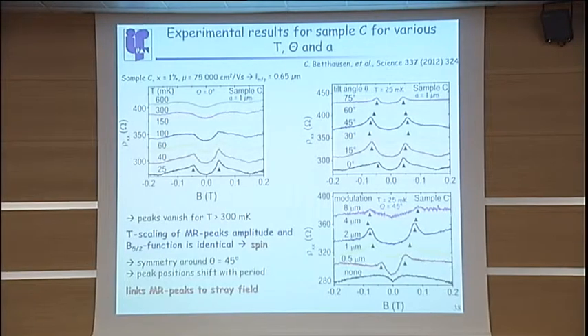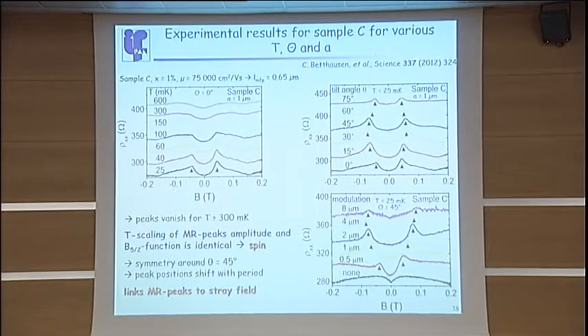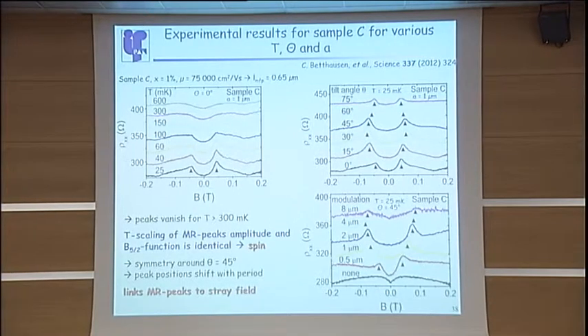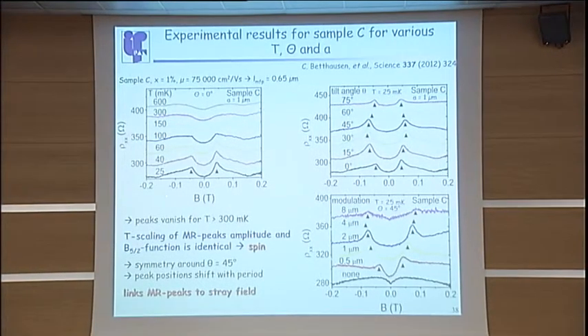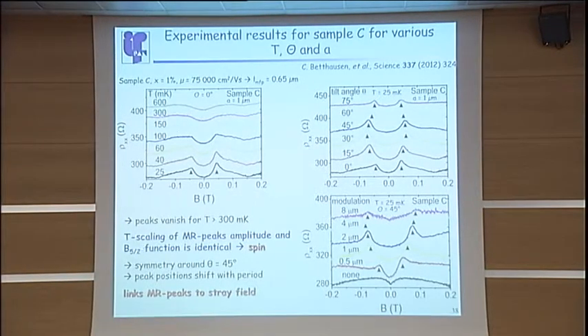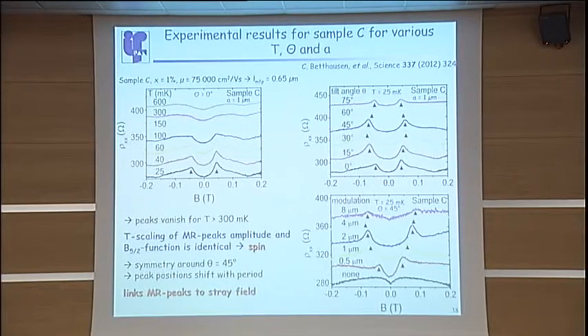And now, in order to demonstrate that this is related to the spin in our structure, you can show this using a normal trick. Namely, you can use the temperature dependence, so you can show that the amplitude scales with the Brillouin function, so the peaks disappear with temperature. Now, in order to relate those peaks to the stray field, you rotate the field at which you magnetize your stripes, and they should, according to the micromagnetic simulation, be symmetric around 45. And you can see this. And also, they should move to higher field if you increase the